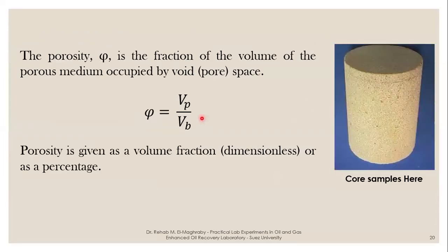The porosity is the pore volume divided by the bulk volume. The bulk volume that I measure for this core is π d squared over 4 times L. This is the volume of the core plug, the bulk volume. If I measure the porosity, I can know the volume of pores that I have. Or the reverse: if I have the pore volume divided by the bulk volume, I can know the porosity. And it is dimensionless, because it is volume over volume.